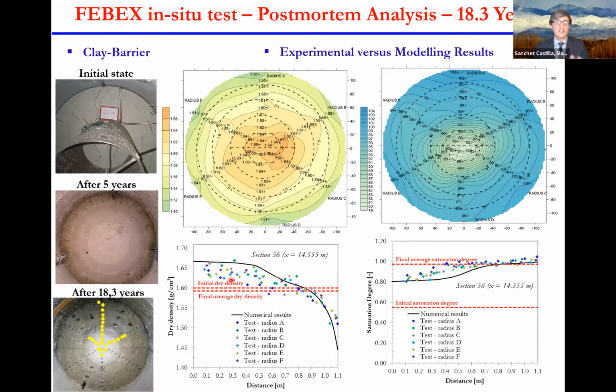These are the same results, but now plotted in a different manner. Here is what happened near the rock, and this is, sorry, close to the canister, and this is as we move away, and this is near the rock. So we have a change in dry density, with a very high density near the canister because of the drying, and very low density because of the expansion, swelling of the bentonite near the rock. And in terms of saturation, at the end of the experiment it is almost fully saturated, but the final part close to the heater is still unsaturated.